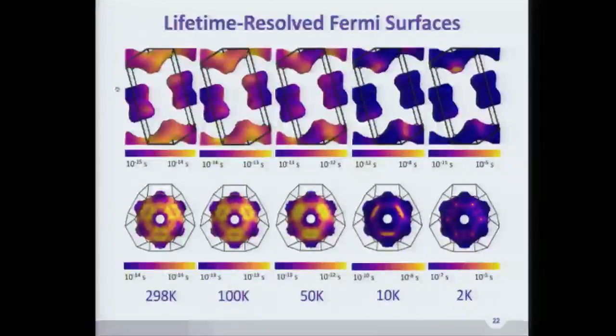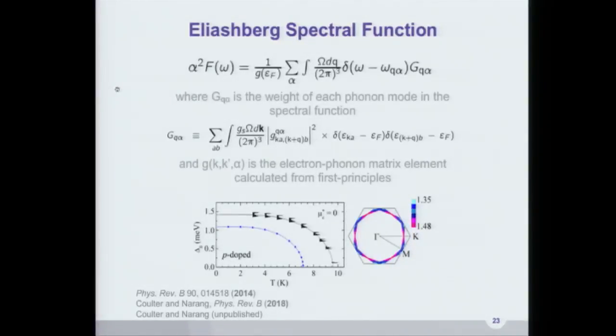And we also wanted to see how these contrast with looking at, say, something like copper at low temperatures. So that also required us to start thinking about how we can extend our own methods, going from this diagrammatic perspective to something that links with what more condensed matter theory folks think about, which is the Eliashberg spectral function. Essentially, the idea here is that we can look at the contributions from different phonon modes, and this could allow us to better understand both the optical properties of these materials, as well as where the violation of the Wiedemann-Franz law is coming from.